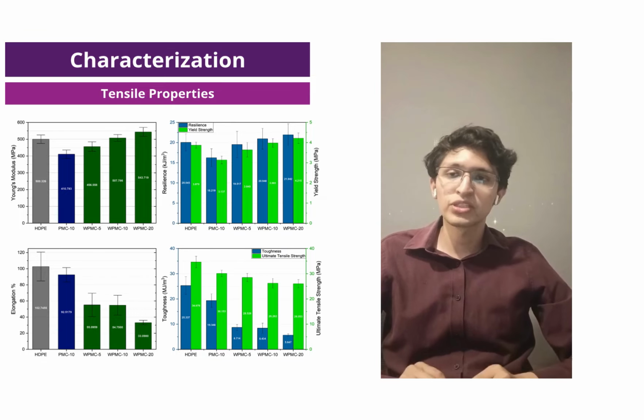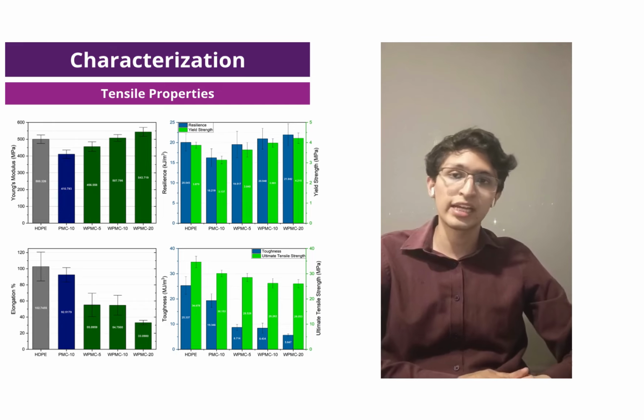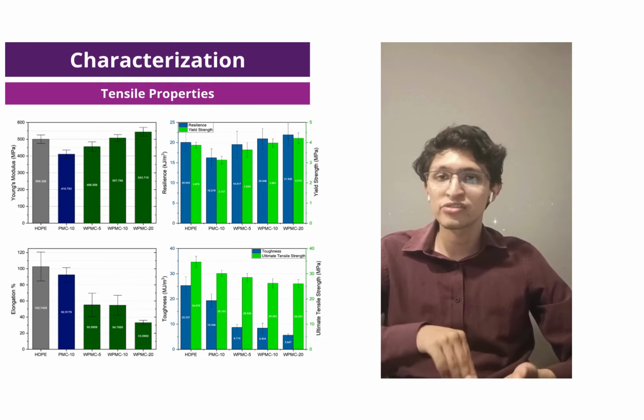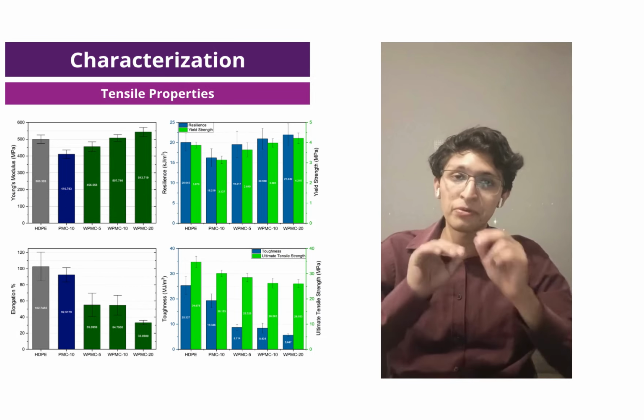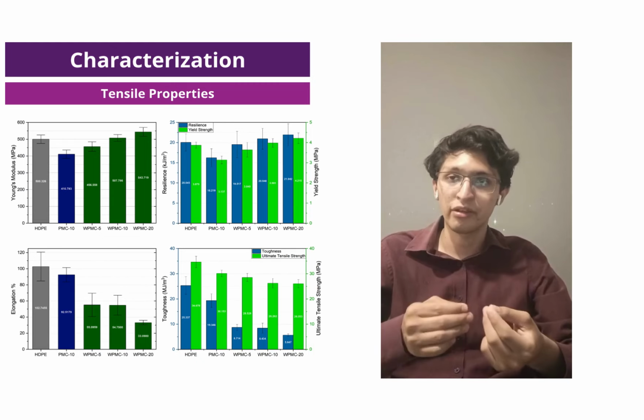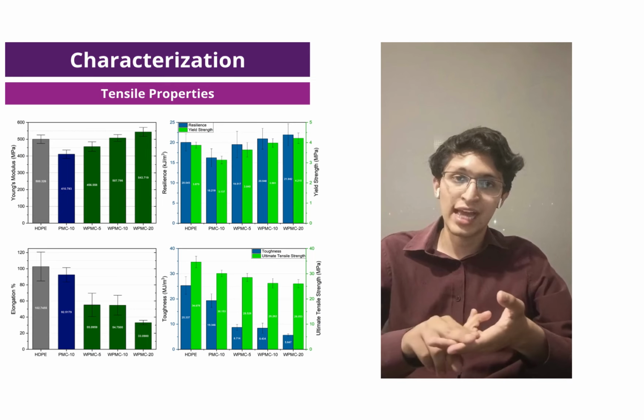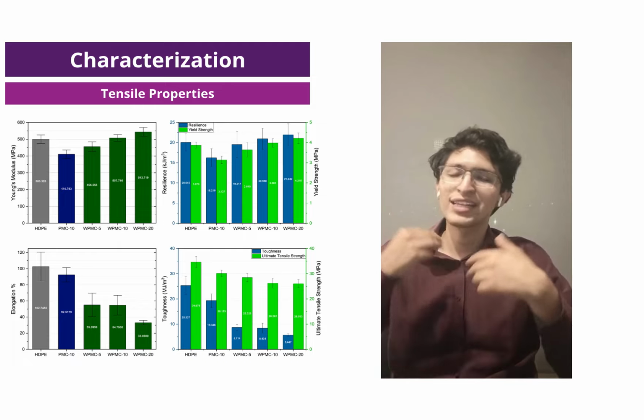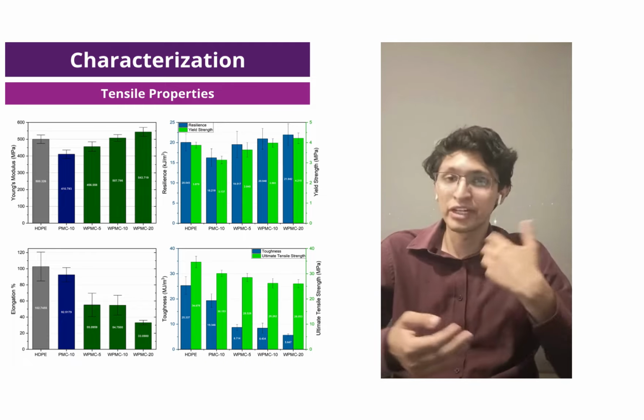These stress concentration points reduce the elongation percentage, the toughness, and ultimate tensile strength of our material. However, it increased the stiffness of the material. Young modulus, resilience, and yield strength improve with this. Why did this happen with the introduction of more multilayer plastics?